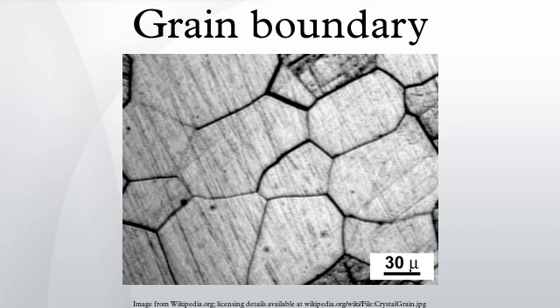The most simple boundary is that of a tilt boundary where the rotation axis is parallel to the boundary plane. This boundary can be conceived as forming from a single, contiguous crystallite or grain which is gradually bent by some external force. The energy associated with the elastic bending of the lattice can be reduced by inserting a dislocation, which is essentially a half plane of atoms that acts like a wedge, creating a permanent misorientation between the two sides. As the grain is bent further, more and more dislocations must be introduced to accommodate the deformation, resulting in a growing wall of dislocations — a low angle boundary. The grain can now be considered to have split into two sub-grains of related crystallography but notably different orientations.